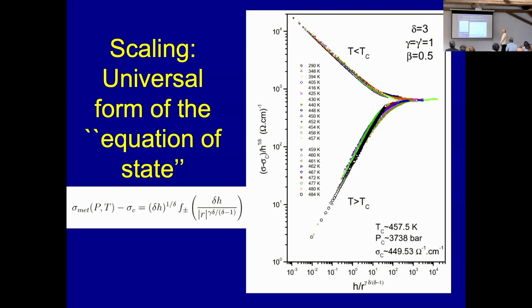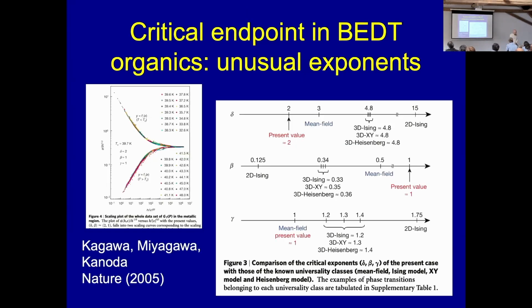Okay, so in Kanoda's group, the same sort of analysis was done on BEDT organics, and well, it came out with a surprise, which is that there is also a beautiful data collapse, but the exponents that come out of this analysis are actually very different from the ones you would expect from the Ising model. Delta, for example, is close to 2, as you see here. Beta is close to 1. Gamma is close to 1.